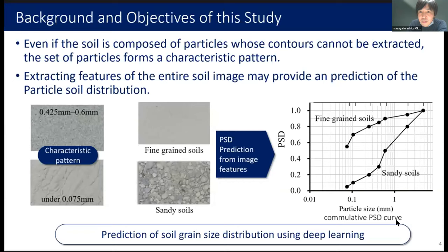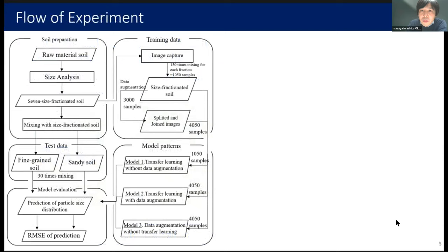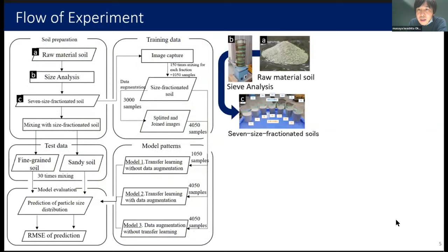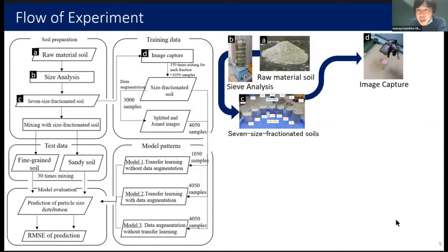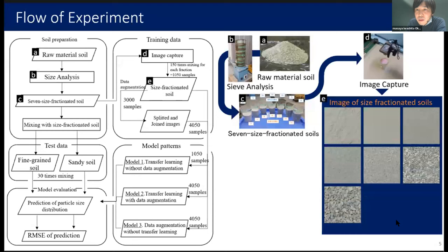The experimental flow is shown here. First, the raw soil is selected. We selected a commercial soil with a wide distribution of the fine grains and gravels. The raw soil is sieved and divided into 7 size fractions. These size fractionated soils are photographed with a digital camera. The size fractionated soil was placed in a container and 150 samples each were taken from the top for a total of 1,050 samples. Since 1,050 samples are not enough to apply deep learning, we augmented the image data for